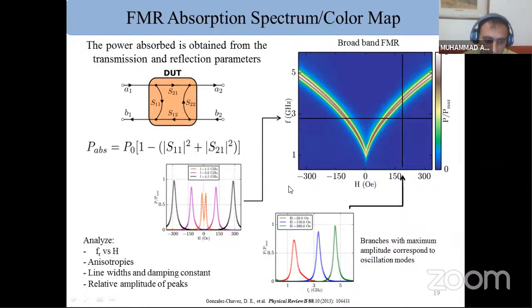The line width and damping constant can also be measured with the power derivatives. We can measure the relative amplitude of the peak. You can see here the relative amplitude of the peak by fixing frequency and fixing field.